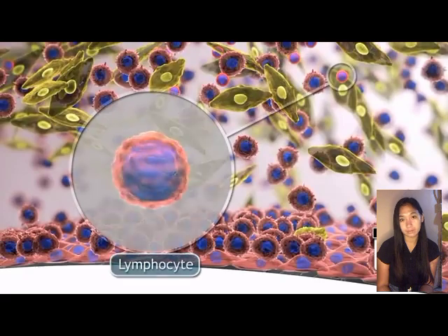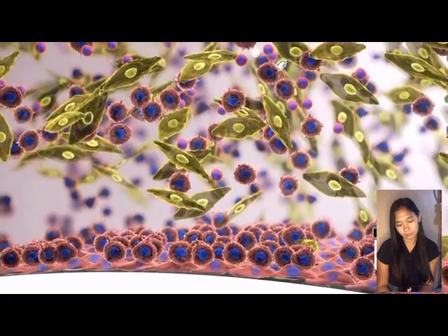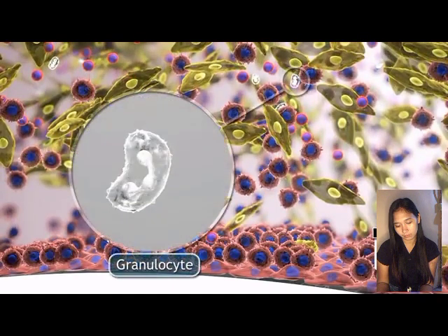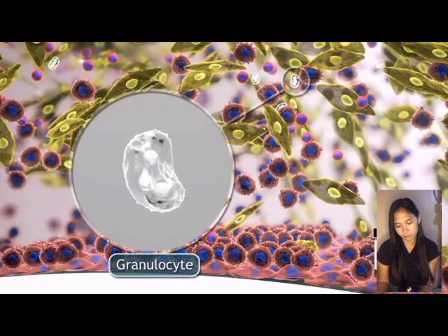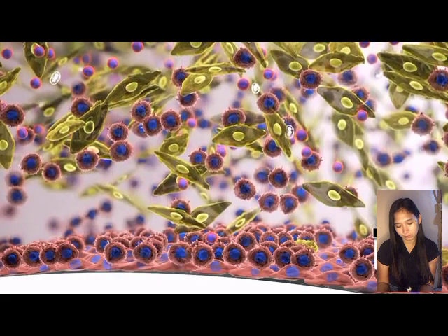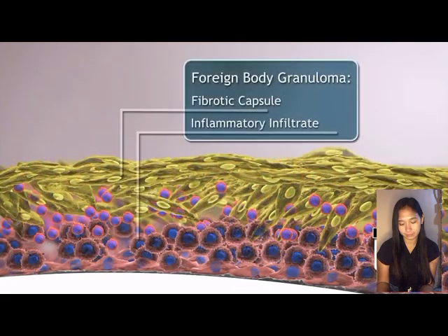Both T lymphocytes and polymorphonuclear granulocytes are present, which disappear as the granuloma ages. As the process continues, the number of cells in the granuloma increases, and after 1 week, an early foreign body granuloma can be recognized with its typical layering. In the interior, the macrophage layer, and outside the fibrous or cicatricial capsule comprising collagen fibers and a great number